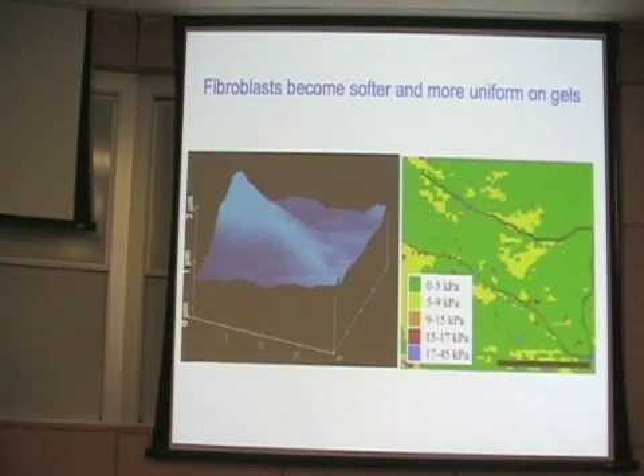Okay. But if we do the same thing and we put it not on an infinitely rigid surface that the cell would never see in vivo, but on a matrix that's relatively appropriate for the tissue where these things come from, two things happen. One is, here's again a color map of the stiffness. Here's the outline of the cell, and this is the gel around it. One is this, a lot of this heterogeneity goes away.